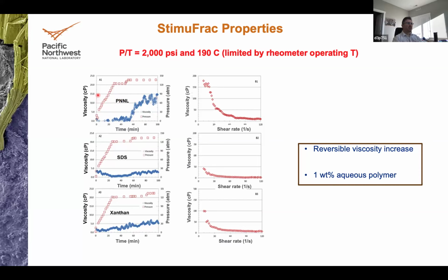And then we can do this over and over again and get viscosity increases. The viscosity is about 15 centipoise. It's not huge, but again, the temperature and pressure limited by the rheometer are in the lower limit of changes in rheology of the polymer solution. If you have a sodium dodecyl sulfate, which is a typical surfactant used in oil and gas, as well as xanthan, there are changes in viscosity, but not as high as in the case of a polymer solution at these temperatures. The fluid also shows shear thinning behavior, so it can be injected or co-injected with CO2 at high shear rates, and the viscosity will be similar to water. So you can pump this as you pump water, and then as the shear rate starts decreasing, and let's say the polymer solution with the CO2 or the polymer solution alone starts getting into the porous network of the rock, the flow rate will start reducing, and you can see that the viscosities are about an order of magnitude higher, to 2 orders of magnitude higher than water, just because of the reaction. Again, this process of viscosity increase is reversible with pressure.